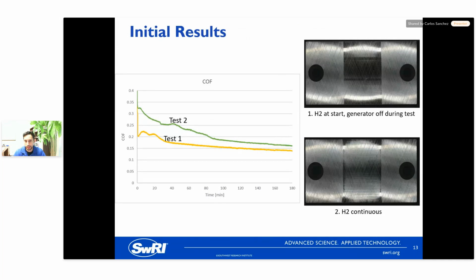So test 1, we ran hydrogen at the start and the generator was turned off during the test. And then test 2, we ran hydrogen continuously throughout the test. So one thing we found is that the way in which you introduce hydrogen to your environment is critical. Because hydrogen gets absorbed pretty quickly into your system, but it also dissipates pretty quickly as well. So if you just have hydrogen at the start without any kind of pressure pushing it into your materials, it kind of goes away and you don't have any real effect on that.